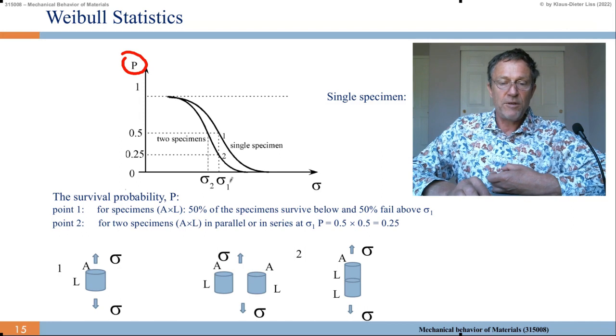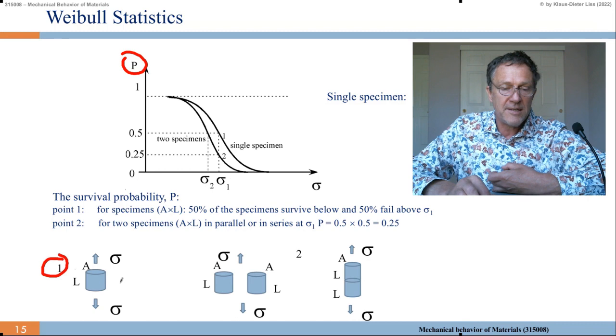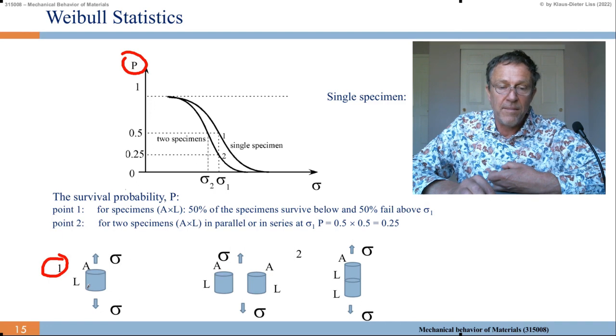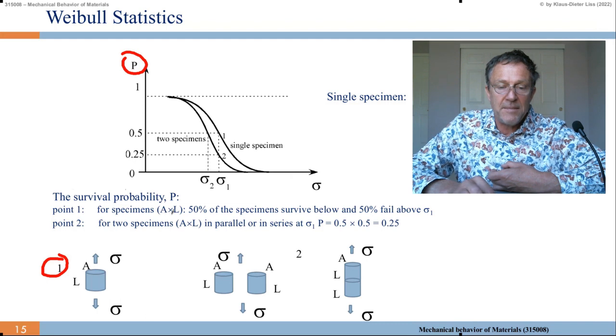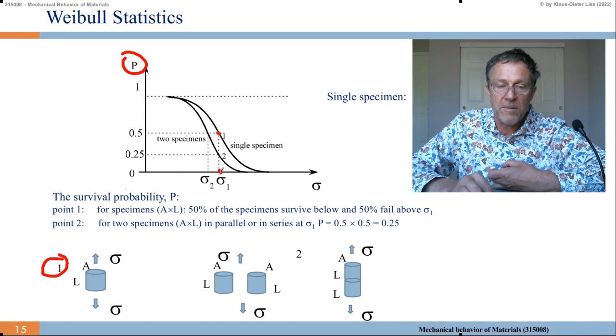And if I look now at two specimens, I look at specimen 1, which has a single volume, and apply the stress sigma. So it has an area A and a length L. So for 1 I get this curve. For specimen A times L, we get, let's say, 50%. I look at that point here, and 50% fail above sigma 1. So this is my sigma 1.